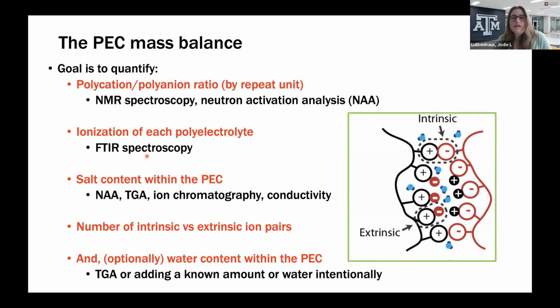We also use FTIR. If ionization is a concern, we can quantify the ionization of individual polyelectrolytes. We want to know the salt content in the polyelectrolyte complexes, because there can be salt partitioning in the solid or liquid phases. So there's a variety of methods we can use here. Taking all of that together, that's going to yield the number of intrinsic versus extrinsic ion pairs. We're also interested in the water content. Sometimes we will dry out the complex and then purposefully add water back, so we know what water is doing to the glass transition and dynamics of the complex.